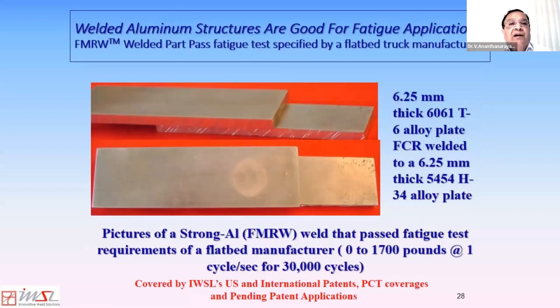And the common thought process with aluminum welded structures is also that they are not good for fatigue loading or cyclic loading. And that paradigm is also broken by this focused melt resistance welding technique. You can see that the 6.25 millimeter thick sheets that I showed in an earlier slide have been welded very cosmetically. If you move your finger across this weld, you will not feel the weld nugget at all. You can see how smooth the outer surfaces are here. And you can also see the grip marks here on the sides of the sheet metal.